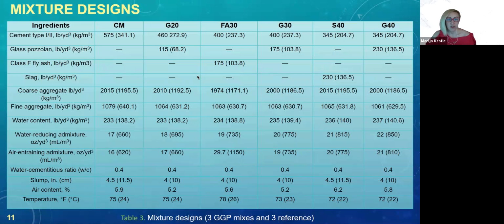Mix designs were developed according to ASTM standards and also according to the Department of Design and Construction of New York City for sidewalk construction. So some requirements had to be followed. For instance, this concrete had to have an air content of 6 ± 1%. Water to cement ratio was 0.4. And there were 3 references: cement, fly ash 30% replacement, slag 40% replacement. So these 3 were references, and 3 mixes with ground glass pozzolan were 20, 30, and 40% of cement replacement per weight.